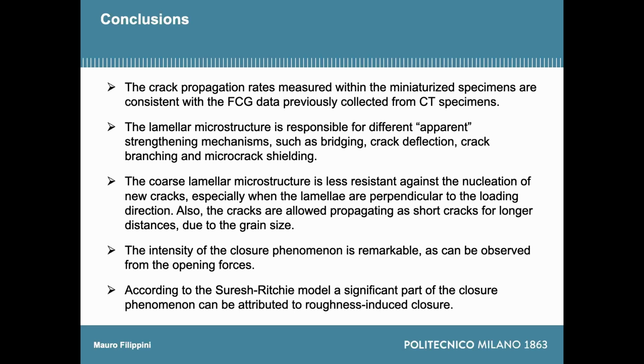The coarse lamella microstructure is less resistant against the nucleation of new cracks, especially when the lamellae are perpendicular to the loading direction. So the cracks are propagating quite fast through the first grains. And the cracks are allowed to propagate as short cracks for longer distances when you have a coarser microstructure. And the intensity of this crack closure phenomenon is remarkable because you have about 35% of closure with respect to the maximum loading in the region of the threshold. And according to the Suresh-Ritchie model, a significant part of the closure phenomenon can be attributed to roughness-induced closure, but it is not all. There is more than that, which is also difficult to highlight.